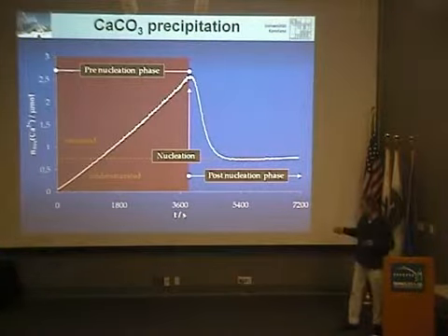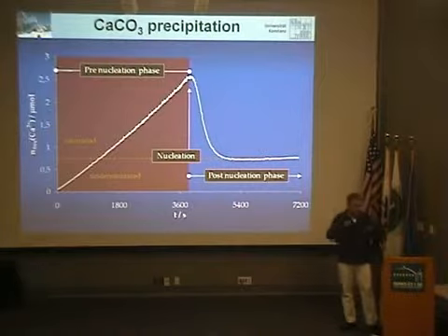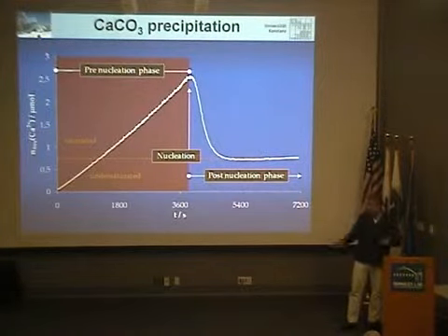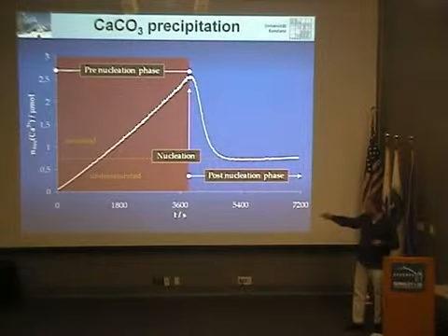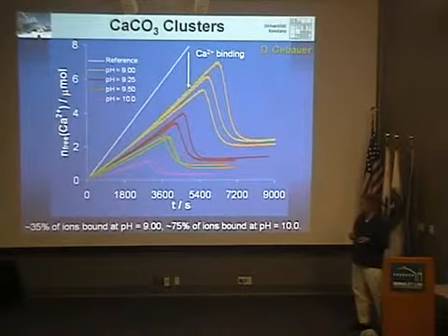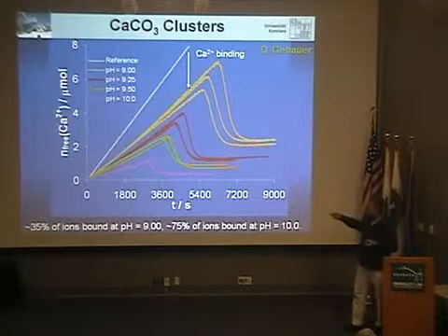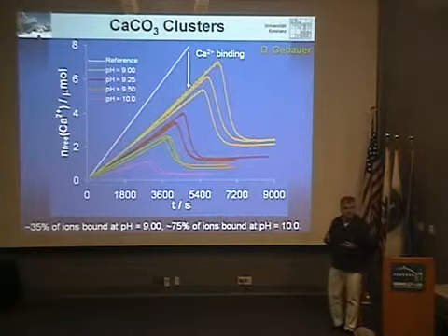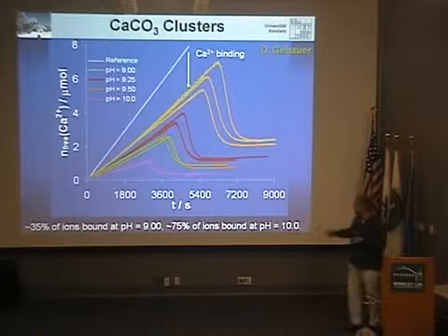So it's a one-phase system. And after nucleation, I have a two-phase system. So I have, for example, amorphous calcium carbonate in equilibrium with the ions in solution. So here, a one-phase system, and after that, a two-phase system. And if I do titration experiments like that at different pHs, I will influence the carbonate-bicarbonate equilibrium, which is clear. So the higher the pH, the more carbonate I will have in my equilibrium.